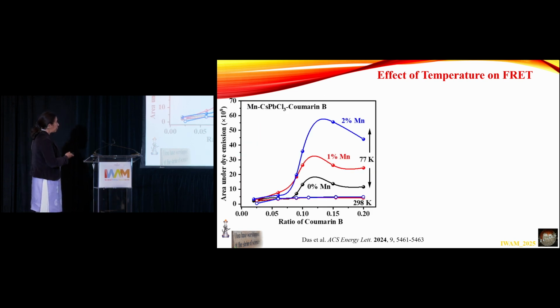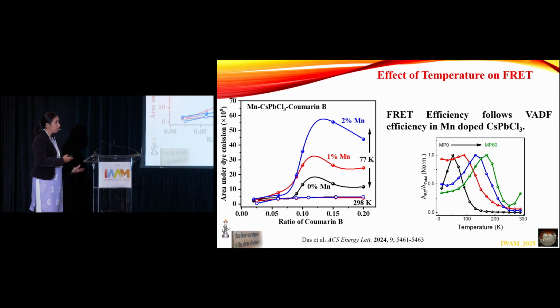So I see that with increasing temperature, at room temperature, whether I have manganese or no manganese, the red and blue are almost overlapping with each other. Whereas when I go down to lower temperature, I see similar effects to what I saw at room temperature. And basically, the black curve is what I am talking about.